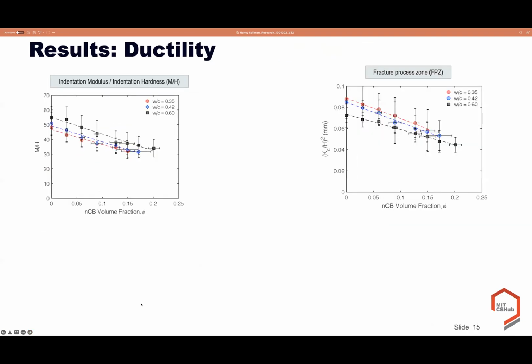So moving now to see the effect of nanocarbon black on the ductility of the cement matrix. To quantify the ductility, we measure the ratio between indentation modulus over indentation hardness as a function of nanocarbon black in the left figure. And we also measure the fracture processing zone, which equals the fracture toughness divided by the hardness, which considers the far field stress in our test, and squared.